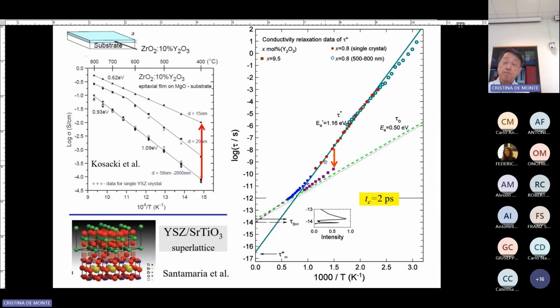So it's like here. When you convert conductivity to relaxation time, of course, this is the conductivity, and the right side is the conductive relaxation time. But there's a formula for it, so it's the same thing. Okay, so you see the activation energy is the same as this one for the bulk. Okay, when you go to here, the conductivity has a much lower activation energy. Okay, so what do you find? You find this thing here. This arrow here is the same length as the change from here to here when you convert conductivity changes to relaxation time change.